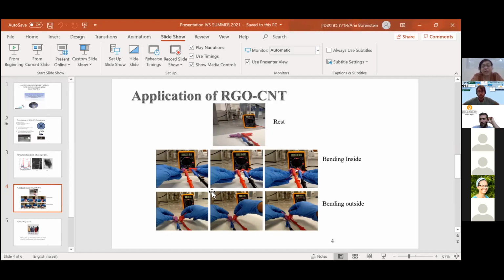This we can explain by the physical properties of the individual layers or the interface between layers, which may be changed during bending. When the electrodes are bending inside, the gaps between layers increase and they lose contact. Whenever the electrodes are bending outside, the gap decreases and they have more contact. That's why the conductivity increases.